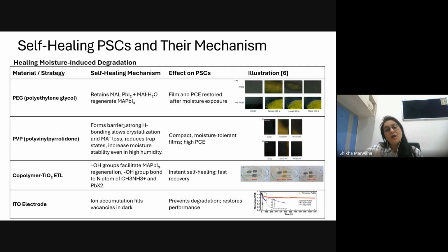Then we have another material, PVP, polyvinylpyrrolidone, in which again, if we see the first figure, in which we have not used this material, we can see that it is repairing itself after a certain amount of time. So if there is MAPbI3 alone, yes, it is getting repaired after certain time. But if we are making use of PVP, we can see that the first figure and the last figure are almost the same. It means that it has retained its phase.